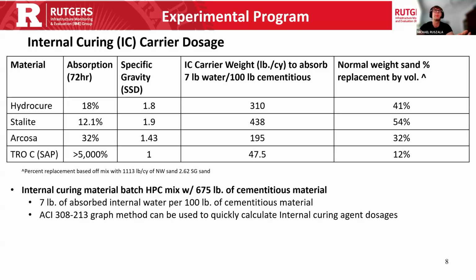So HydroCure at 18%, you need something like 300 pounds. Stalite, lower absorption, you need something like 440. Arcosa with a very high degree of absorption, you require less at just around 200. And then the SAP product, which is effectively pure water in a bead form, just suspended in that polymer, requires even less. And there is a tool that's used for the dosing to quickly calculate it.